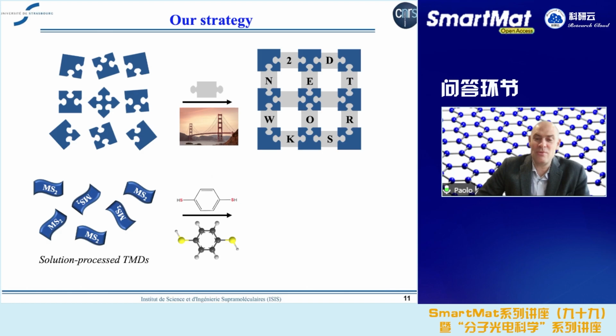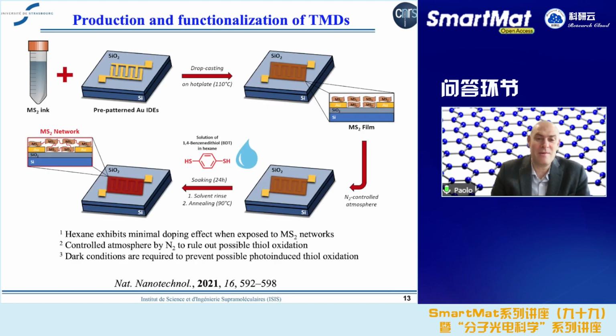The only thing that one has to watch out for is to remain with, let's say, molecules that are highly soluble in solvents that are as apolar as possible, because when you start playing with a polar solvent, this can become a strong dopant for the 2D material. Okay, and that is the reason why here we have actually been using hexane as a solvent for the 1,4-benzenedithiol.